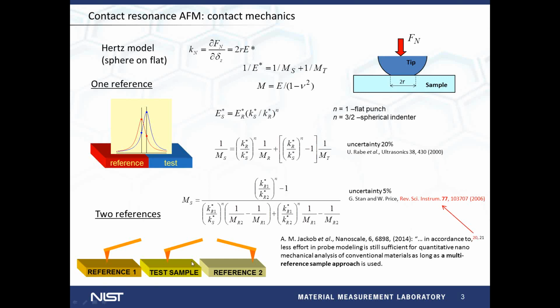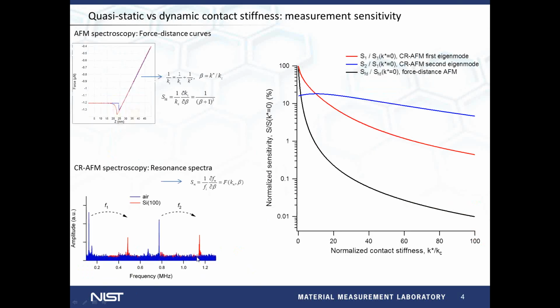And even better measurements can be accomplished when we use two reference materials with elastic moduli that bracket the elastic modulus of the test material. The question is why we need contact resonance, because we already have force distance curve measurements, and basically we are looking at the same parameter, contact stiffness. And the answer is that with contact resonance, we can extend the range of the elastic moduli that we can measure. And the hint is showing here in this plot of sensitivities of the two techniques.